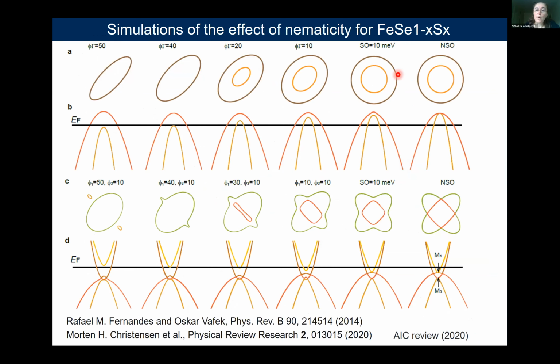And here at the top are the simulation for the hole bands, where I put some realistic numbers from experiments on the tetragonal system. This is only turning the spin orbit coupling on. We have a finite band splitting for the hole bands, but increasing the nematic effects, these shifts will occur. One band keeps shifting down, and then the inner hole pocket will disappear. Whereas for the electron bands, they are a bit more unusual because they are formed of two crossed ellipses, and we have these two degenerate points.